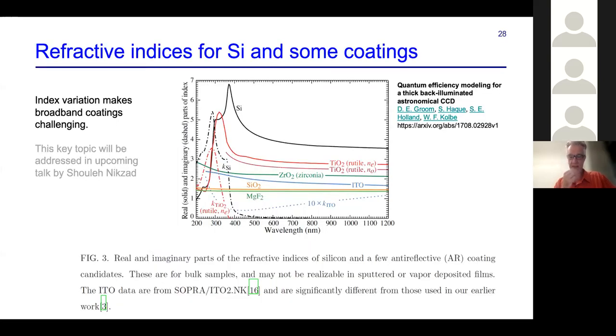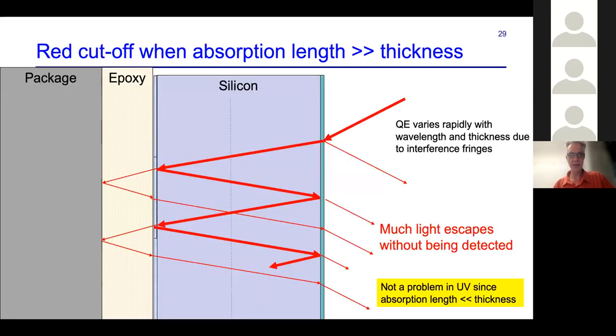the backside AR coating problem is fairly significant because these plots show you silicon in black and various other materials going through quite violent changes in refractive index in the range of wavelengths that we're interested in. And so Shouleh's group work extensively on developing coatings that can cope with this. I'm not going to get into it myself. I'd rather stick to the schematic part of the detector layout.